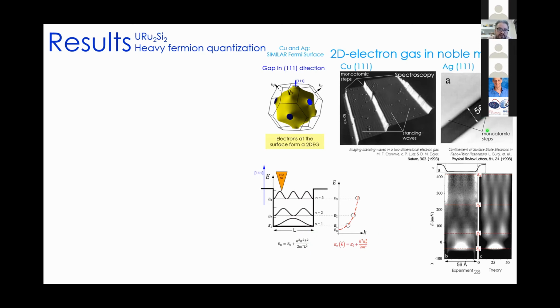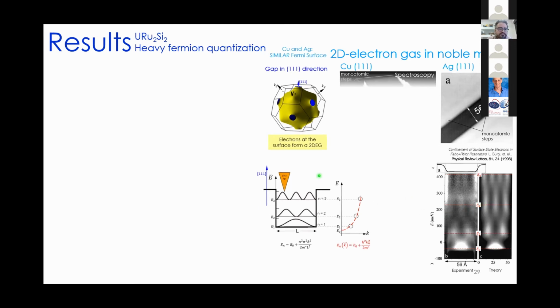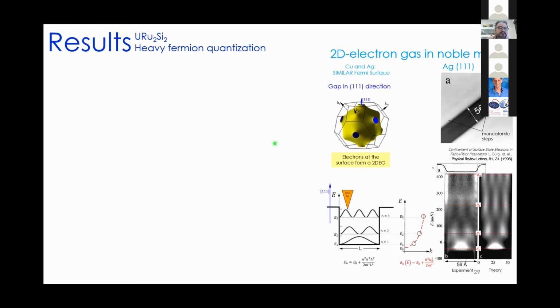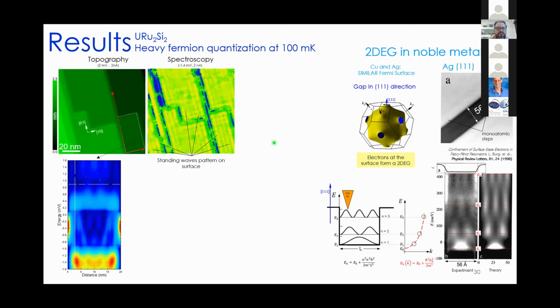Here for the silver, there is another type of representation of the density of the states as a function of the energy and the distance. And here the quantization is more evident, where they represent the quantum levels with the red lines. And let me put this here, okay? And let's go back again to the experiment. So we focus our attention on this terrace. Well, here we average the density of the states in this direction, parallel to the atomic lattice. This is the result that we get.